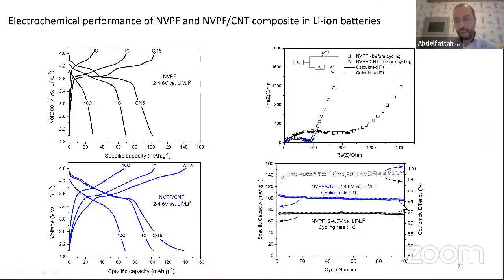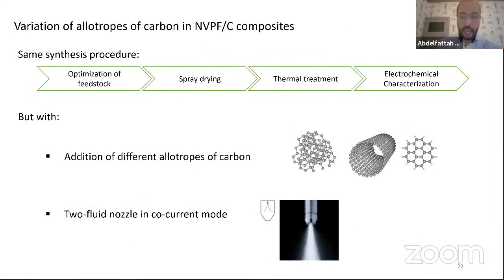We can see that we have very stable capacity over 100 cycles with almost 100% of capacity retention for both materials, but with the highest capacity for the one with carbon nanotubes. After these positive results using carbon nanotubes, we tried to use other sources of carbon. We use carbon black and also graphene.